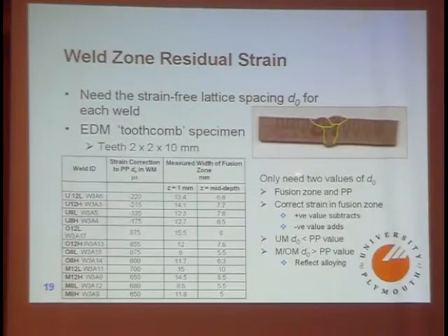But the simple thing is you only need two values of D0. Sometimes you get a variation across the weld, but in steel it looked as though you get away with two values, one in the fusion zone, one in the parent plate. So once you've got this, you can then correct the data. This, by the way, looks quite reasonable because the undermatched had different alloying elements. When you looked at it, you'd have substitutional alloying here, and that should be a larger strain than it is.